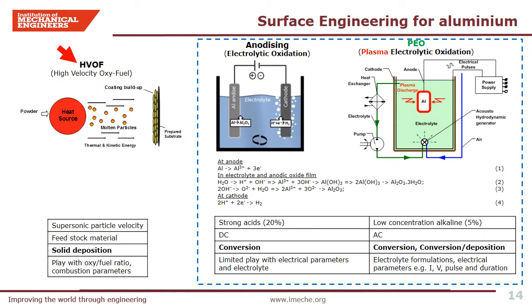The high-velocity oxy-fuel process has been common in industry for depositing wear-resistant coatings on steel and other substrates. But on aluminum substrate, the process is still challenging due to large CTE mismatch between the substrate and the deposited materials. It is a line-of-sight process where the coating material in the form of spherical particles are heated using an oxygen-fuel mixture to high temperature and propelled towards the substrate at supersonic velocity. The nearly molten particles on impact adhere to the substrate, and adhesion is mostly by mechanical keying or interlocking.